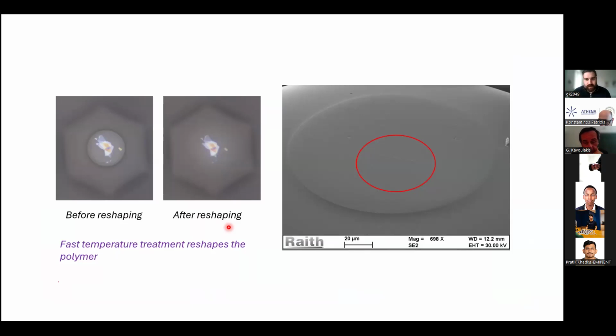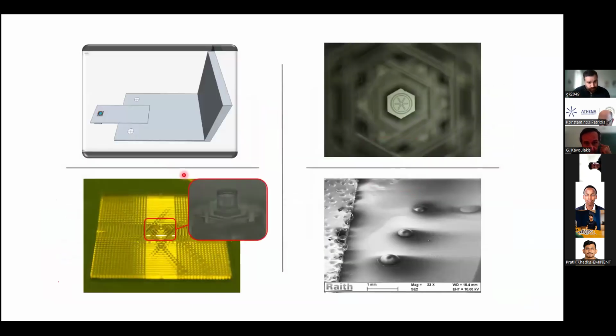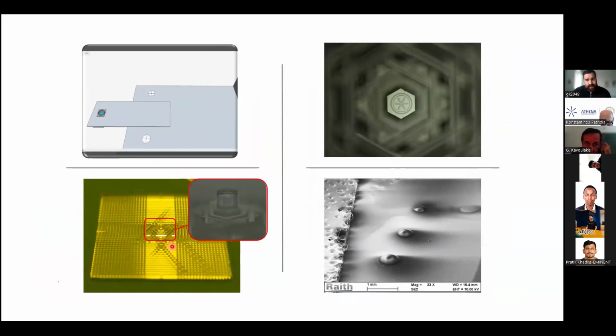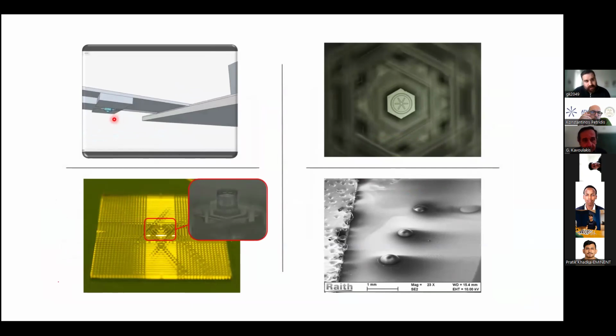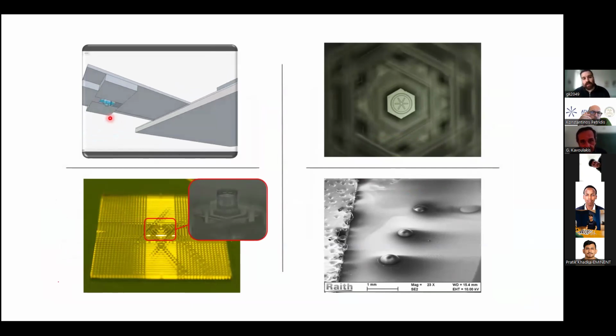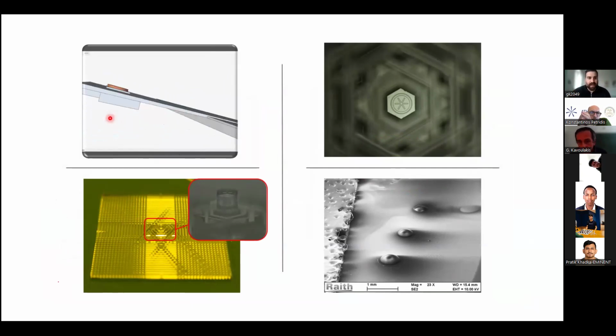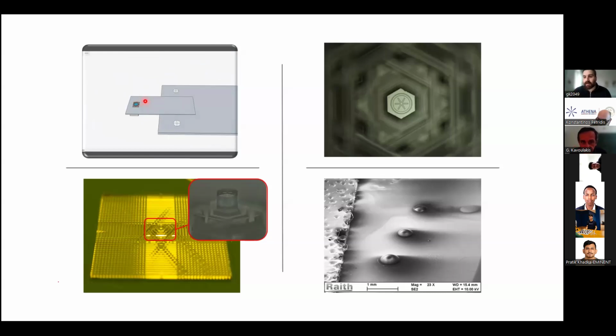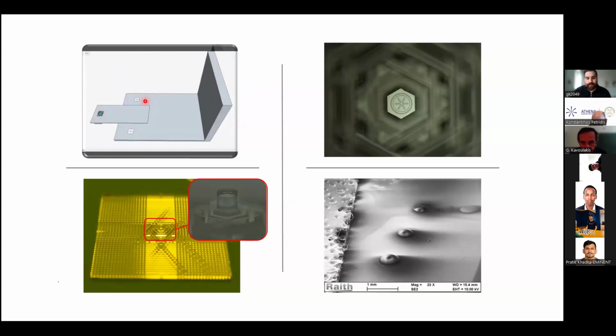It's very time consuming. So for that reason, we redesigned the glass pillar to this square where we can include it in this customized stage, in this socket. It will extrude from underneath like this, so it's going to be the first thing every time to come in contact with the flakes. And on top of that, we included a ring-shaped peltier that will do in situ reshaping. So we don't need to take it out. We just need to wait for 30 seconds, 1 minute to reshape and then go for the next flake.